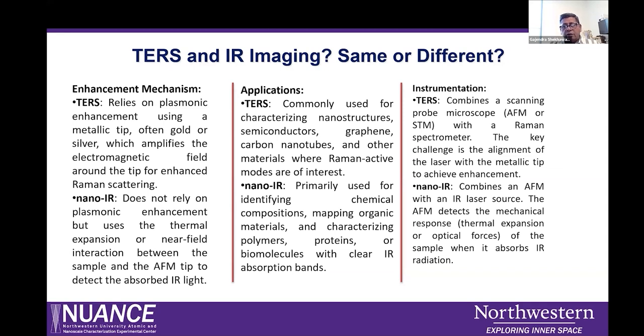And then in the case of nano IR, there's no limitation as such. The depth resolution is about 100 nanometers. It can go up to 100 nanometers with contact mode. TERS, and the tapping mode IR imaging, is more surface sensitive. It's not limited to just semiconductors. You can do a lot of proteins or biomolecules, polymers, because most of these proteins and polymers nicely absorb the IR. Okay, so that's the difference here.